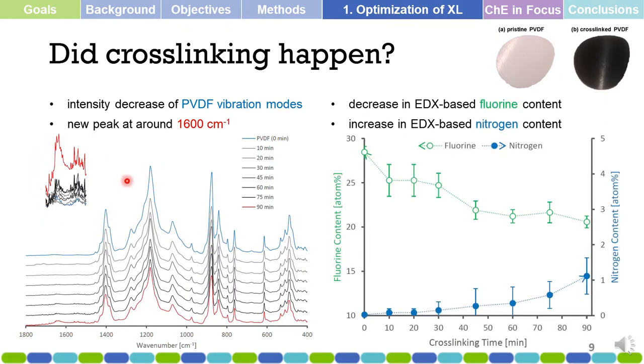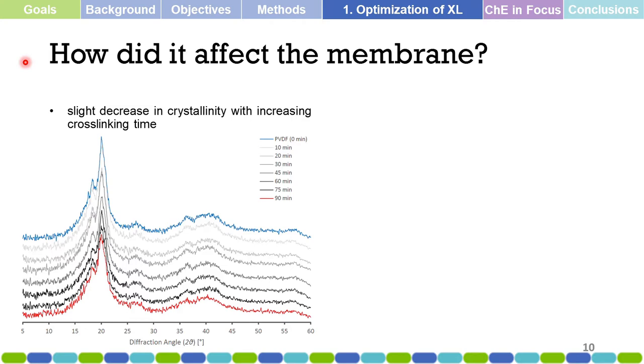To further confirm, we examined the energy-dispersive X-ray spectroscopy data of the membranes cross-linked over time. We can see that the general amount of fluorine in the membrane decreases — due to dehydrofluorination — and then there is an increase in nitrogen content in the membrane, which is due to cross-linking via the diamine (HDA) cross-linker. In this way, we can confirm that cross-linking did indeed happen.